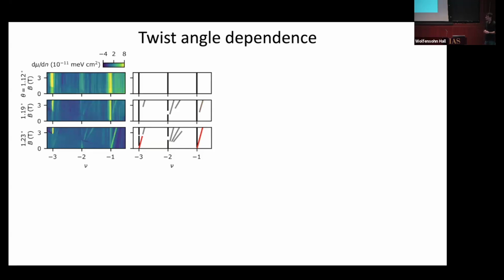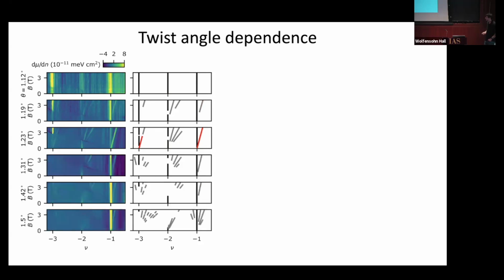If you go to a lower set of twist angles down to 1.12 degrees, you see that instead of having a diagonal feature all the way down to zero magnetic field, the preferred state is just vertical at nu equals -1. So these now, in the low twist angle limit, are topologically trivial states, not quantum anomalous Hall insulators anymore. And similarly, as you go to higher twist angles, here I'm showing up to 1.5 degrees, if you look carefully at this nu equals -1 state, again, everything is completely vertical all the way down to zero magnetic field. And so the topology, the quantum anomalous Hall physics that we observe, is limited to a very, very narrow window right around 1.25 degrees or so.